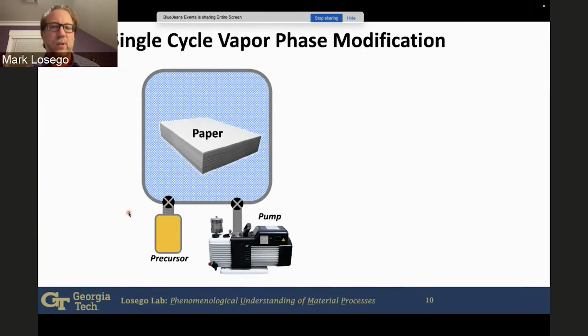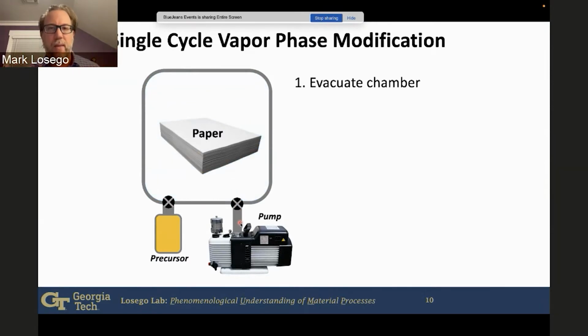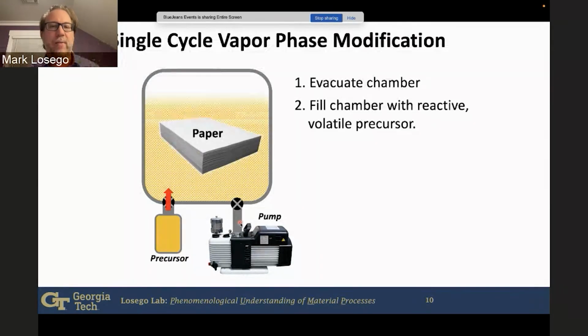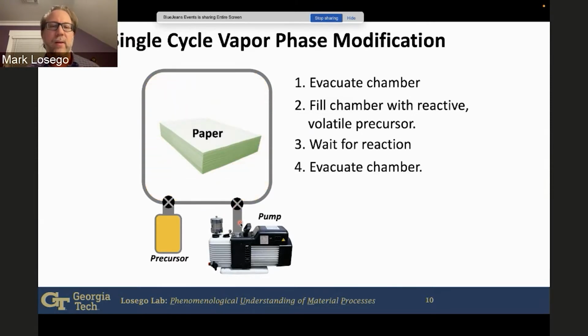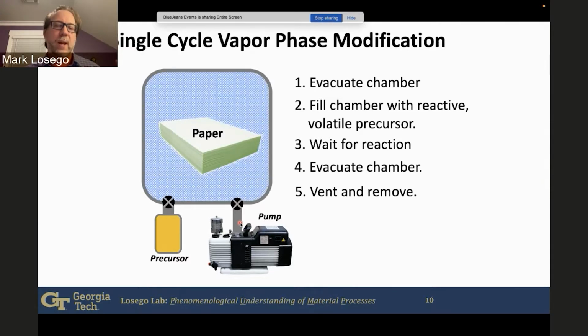So what does this process look like? It's fairly simple. You have a vacuum chamber, basically a stainless steel container that's attached to a vacuum pump that we can suck the air out of the chamber, and these here are valves. We open the valve for the pump, we suck all the air out of the chamber. We then backfill that chamber with this gaseous precursor that we want to use to react with the surfaces and coat the surfaces of our material, and then we wait for the reaction to happen. We then again evacuate that precursor, and then we vent it to atmosphere.